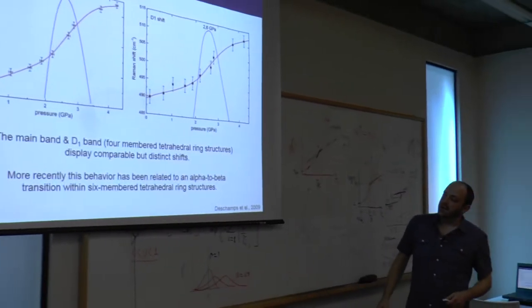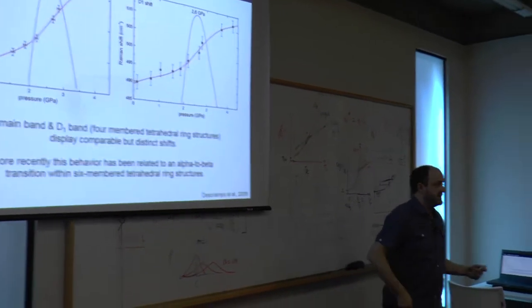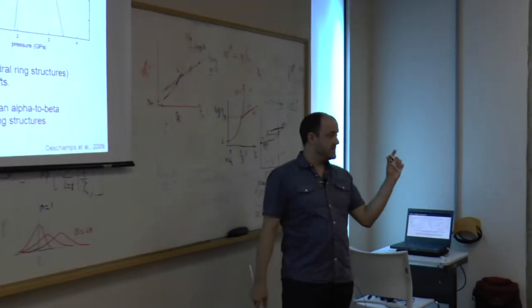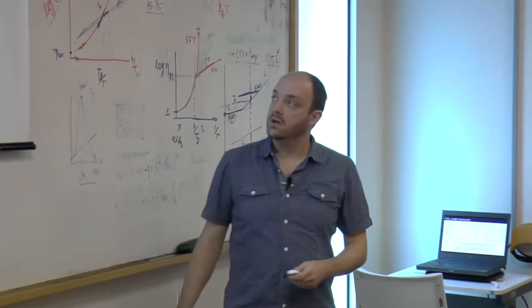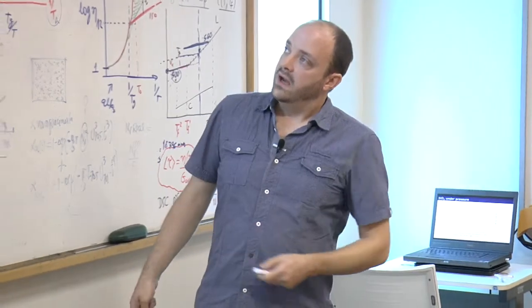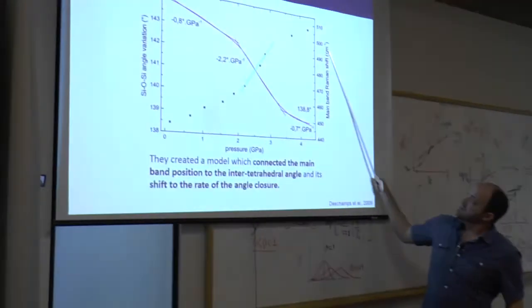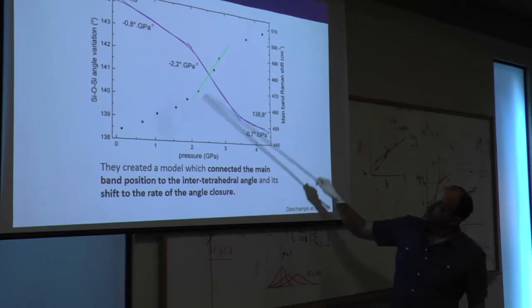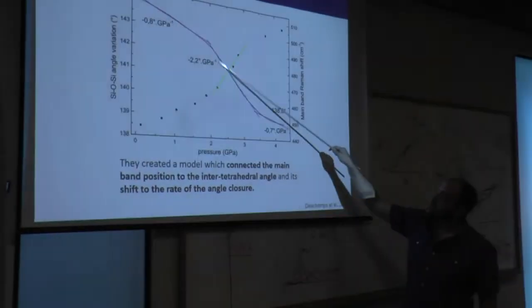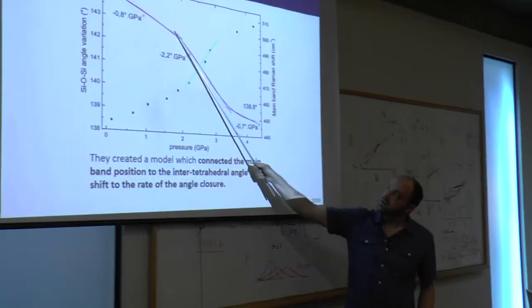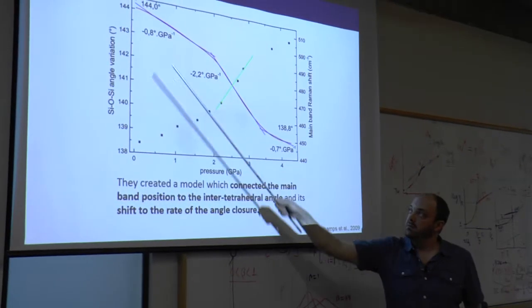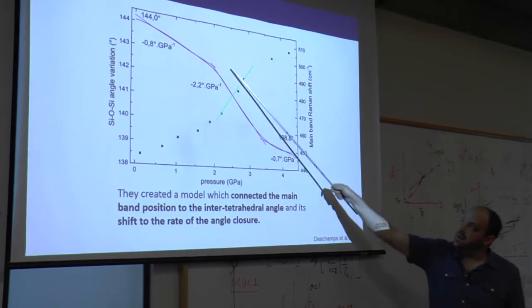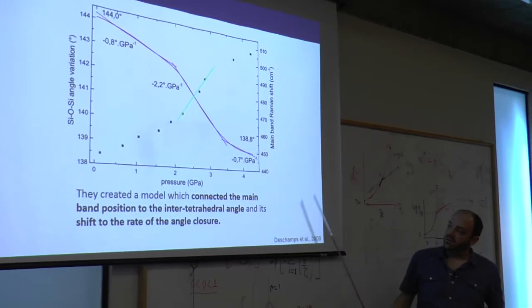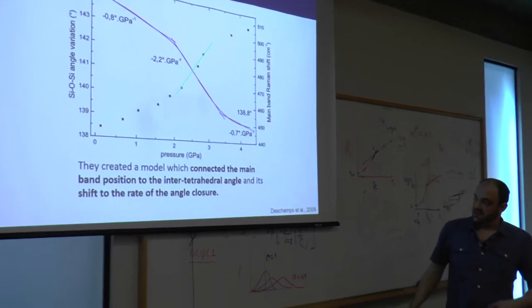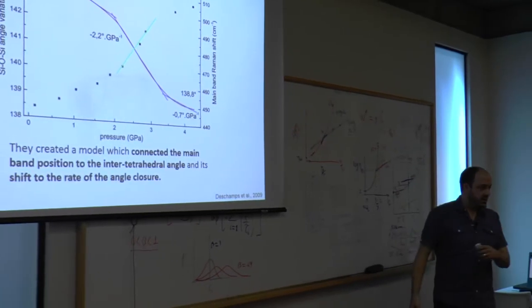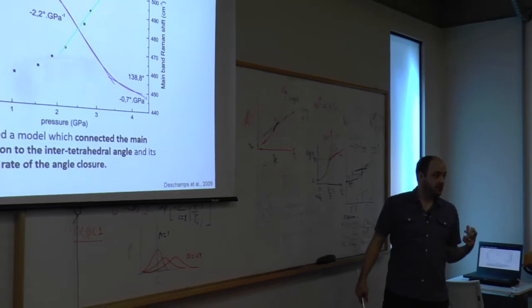And so they actually use these two bands, plus an idea of how the frequency should change as the intertetrahedral angle is adjusted. And they came up with a model that compares this Raman shift here with the actual change in the intertetrahedral angle. And they said at low pressures, it shifts by -0.8 degrees per GPa, then it has this strong shift around -2 before it tapers off again. So this is one way to connect the bridging oxygen vibration with the intertetrahedral angle and what's happening with your sample.